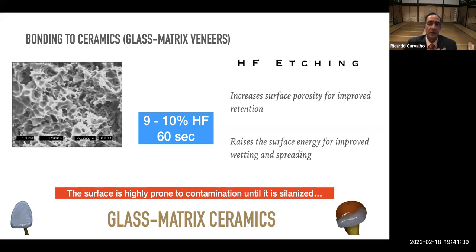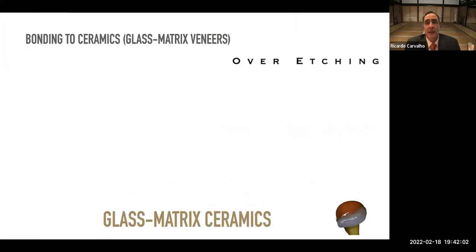That's when, let's say, the most critical aspect of bonding to ceramics starts. After we etch the surface with hydrofluoric acid, the surface becomes highly prone to contamination because we are raising the surface energy. Everything that touches the surface from that point on will readily spread on the surface. There is an issue because, as I mentioned, some ceramics are different than the others. So the average 60-second etching time is an average that is applied to all ceramics. But there are certain cases in which we over-etch the surface.